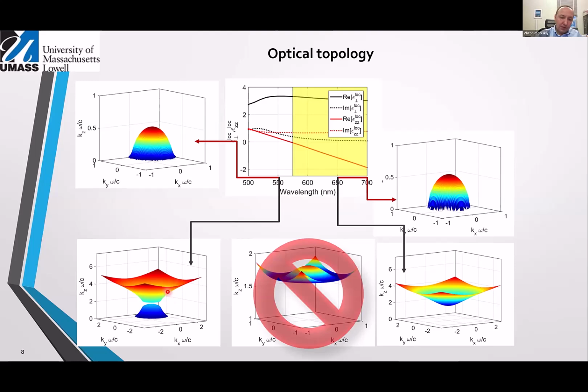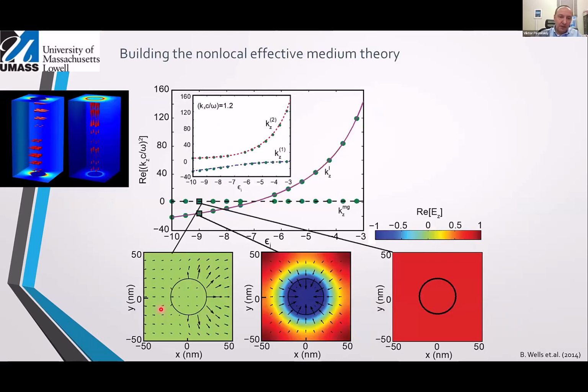And so if we want to put the second mode into effective medium response, then what we can do, we can say that our effective medium parameters now depend on the wave number. So the extra mode originates from the surface plasmon polaritons that propagate on nanowires. And you can see that on average, if I average this field over a unit cell, I do get longitudinal field dynamics because the mode would propagate up the nanowire, and the electric fields that you can see here, they are pointing in the same direction.